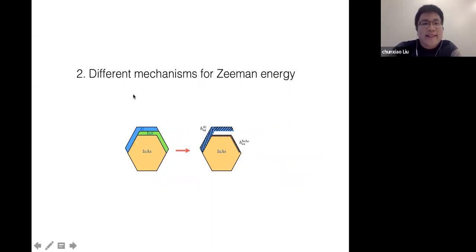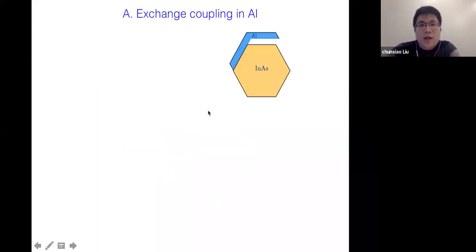Next we will explore in detail different mechanisms for inducing Zeeman energy in the hybrid system. We will study two different mechanisms. One is what we call the direct effect between indium arsenide and europium sulfide, which is modeled by a local exchange coupling term, and the other is an exchange coupling inside the aluminum layer due to the aluminum-europium sulfide proximity effect. First we study the exchange coupling in aluminum and ignore the direct effect between indium arsenide and europium sulfide. So we first focus on the case where the exchange coupling in aluminum is zero.